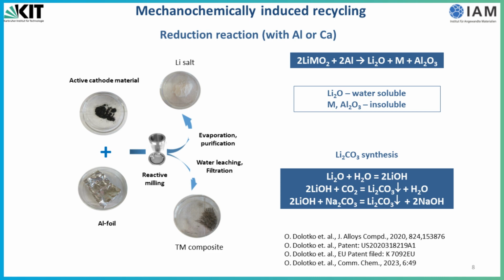If we take a look at all the products of this mechanochemical reaction, we can see that only lithium oxide is a component which is water soluble. The rest of the components, like metals, cobalt, nickel, manganese, or aluminum oxide, are not water soluble, therefore can be separated from lithium oxide by simple water leaching and filtration.